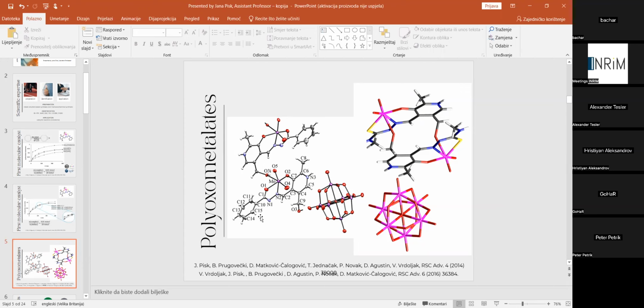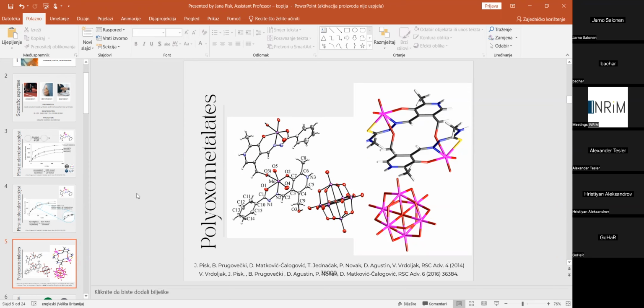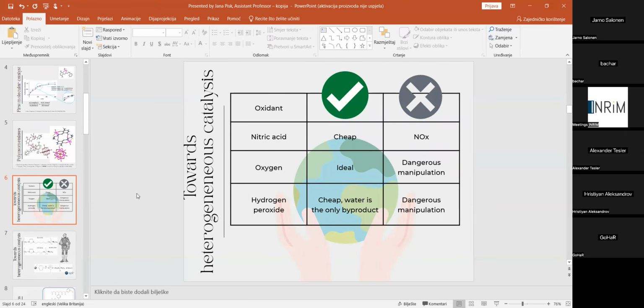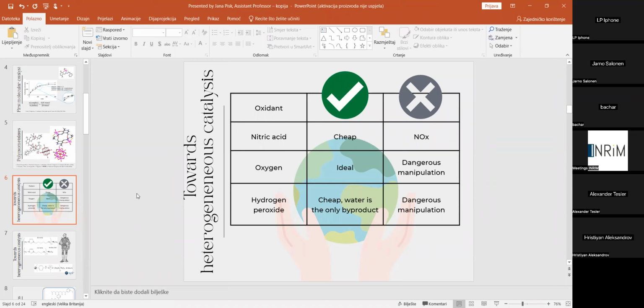We also tested these kinds of complexes under green protocols. So again, we didn't want to add organic solvent to the reaction mixture. We used cyclooctene as a substrate and TBHP in water as the oxidant. As the research continued, we again got quite good results, and we suppose that these complexes have two active sites: one active site comes from the Lindqvist type of ion, and the other catalytic site comes from the simple molybdenum coordination complex. We understood that the reactions we presented were in the area of homogeneous catalytic processes, meaning the catalysts used were in fact molecular catalysts.